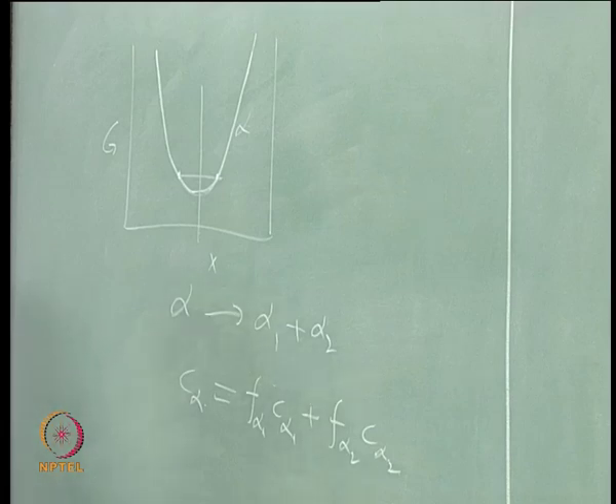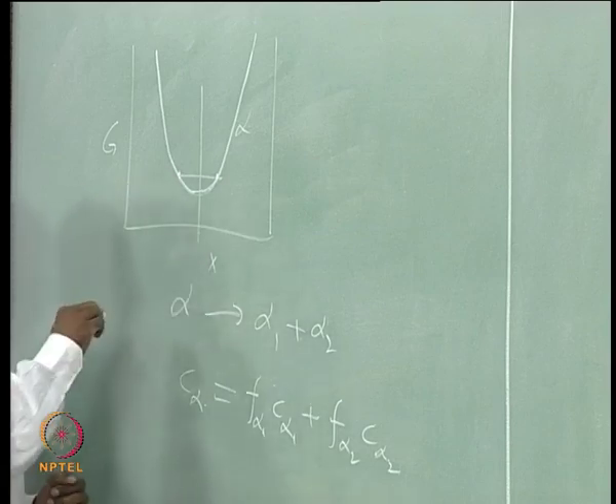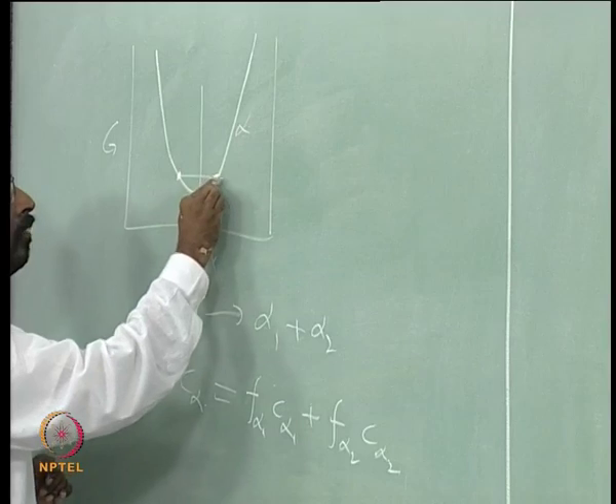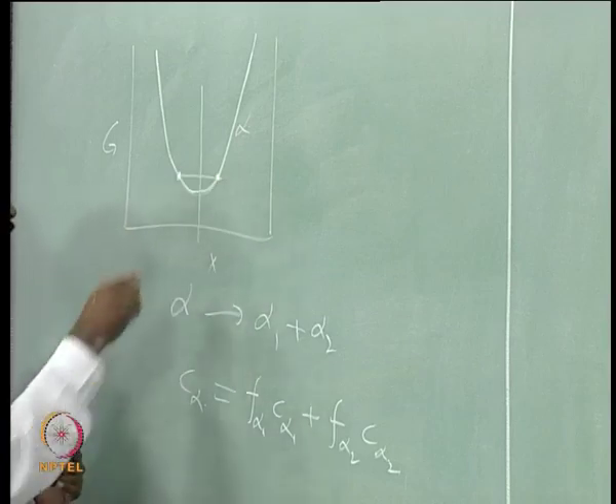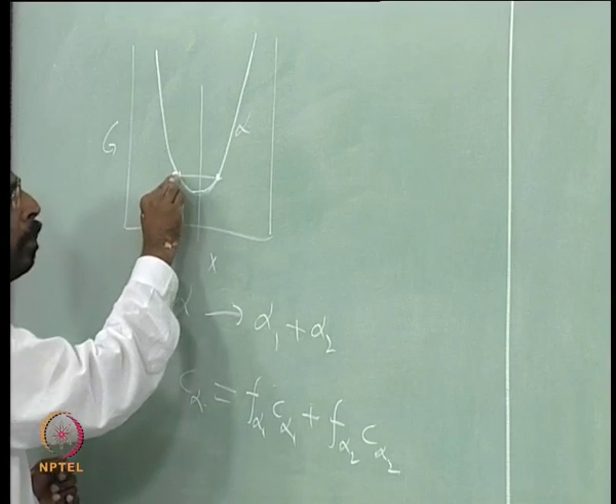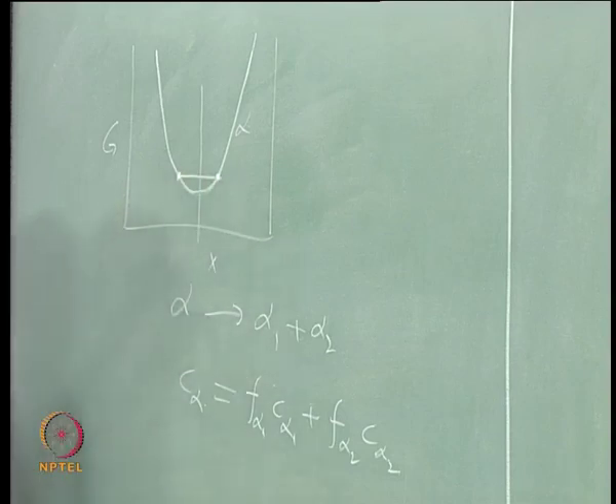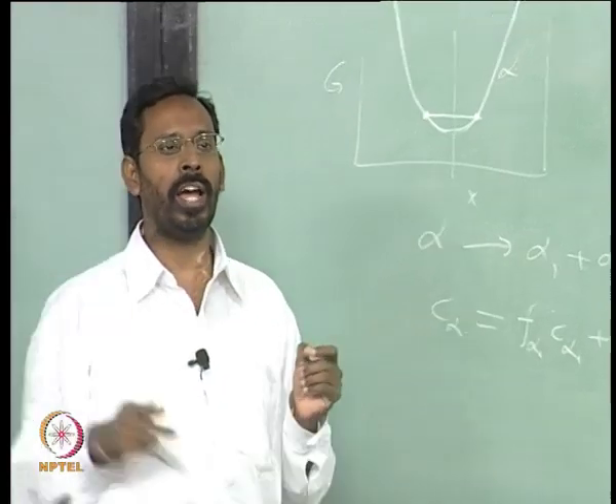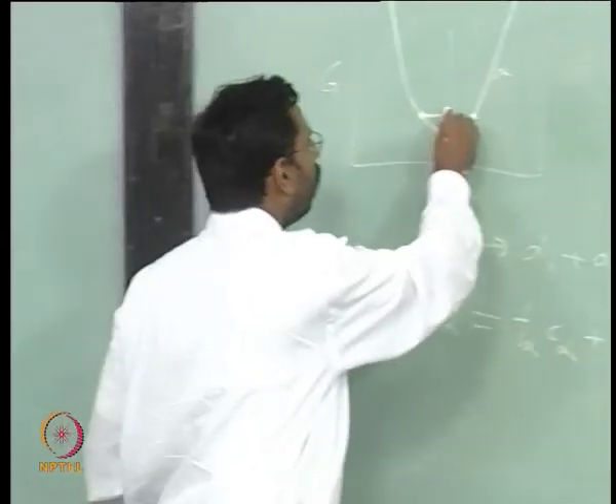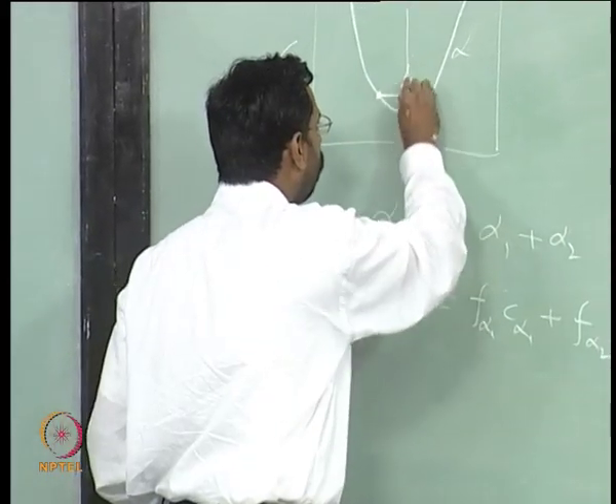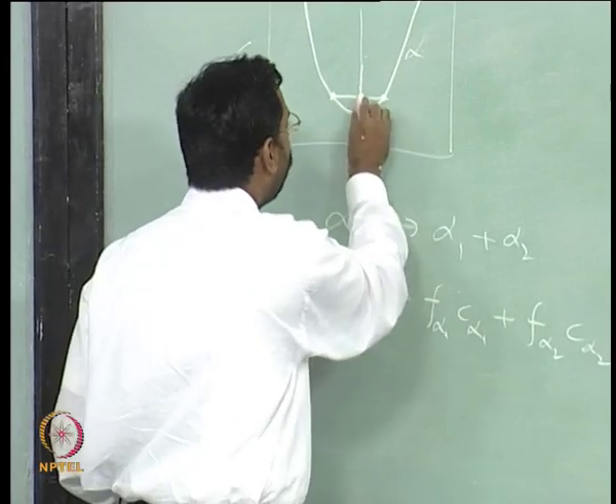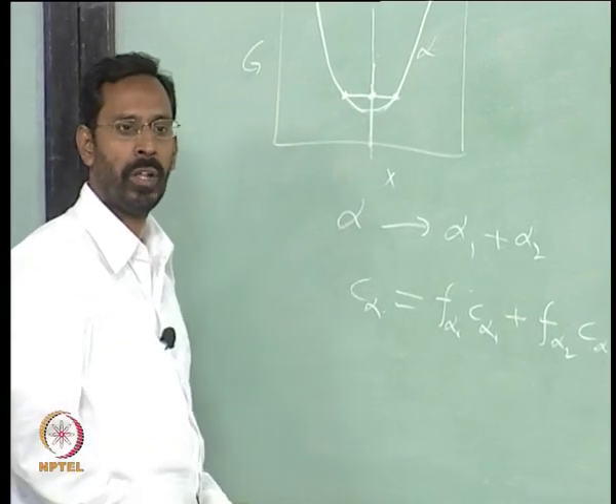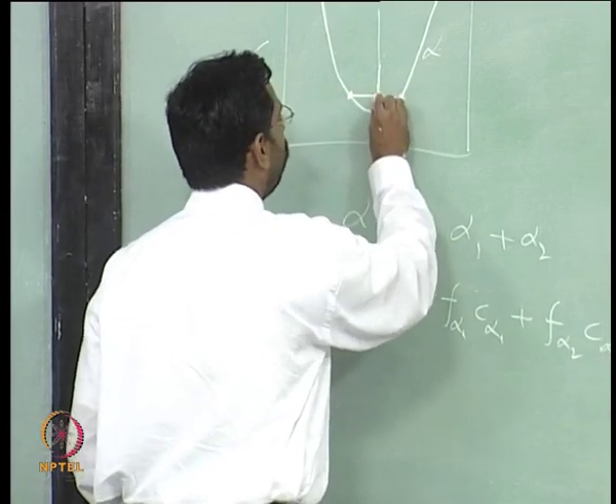For such a process to happen, what is the overall free energy of such a mixture? If this is the free energy of alpha 1, this is the free energy of alpha 2, then the mixture will always have a free energy which is decided by the line joining those two. For any two phases having two different free energies, if you want to know the free energy of the mixture, you simply draw a line joining the two, and for the composition of interest to you, if I choose this alloy composition having these two phases, the free energy of such a mixture is this. This is the two phase free energy.